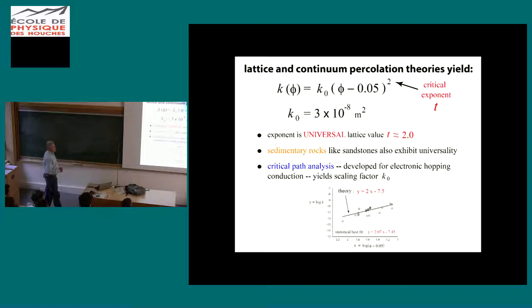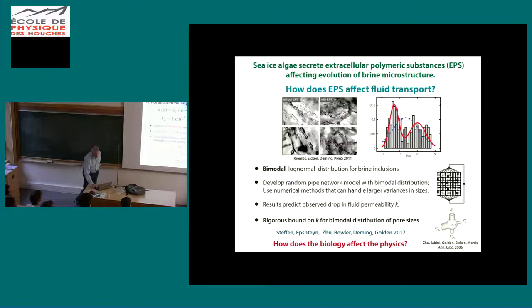Sweeping a lot of lattice and continuum percolation theory under the rug, this is a deceptively simple formula for the vertical component of the fluid permeability in columnar sea ice. There's the 5% where it takes off. This is the best known estimate for the critical exponent, and my upper bound was 2. It's interesting that my upper bound seems to coincide with the best known numerical estimates of the value of this critical exponent in 3 dimensions. And this K naught is not a fudge factor. It comes from critical path analysis, developed originally in the context of electronic hopping conduction in doped semiconductors. We compute that from the X-ray tomography, and then you see how well the theory correlates, at least this version of the theory correlates with data.